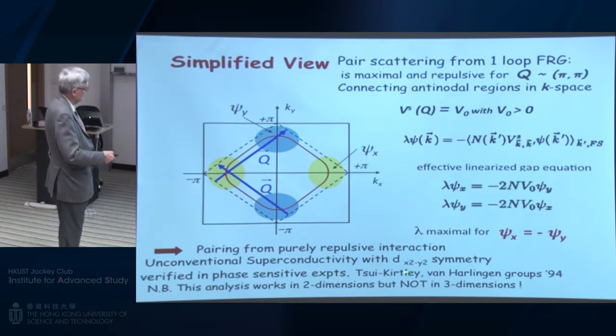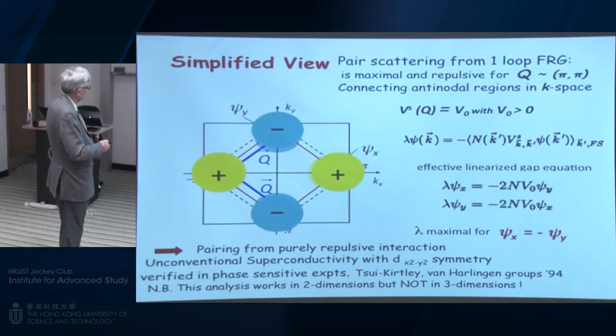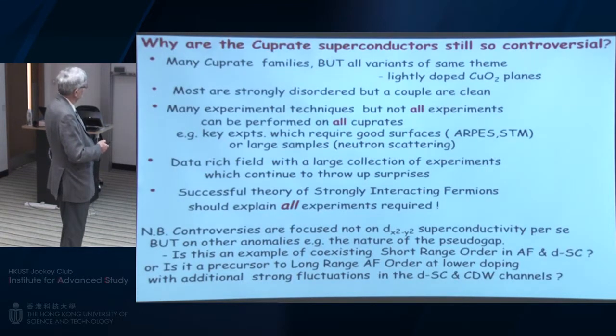It should have this extra phase, and this was then verified by beautiful phase-sensitive experiments in the mid-90s that I don't have time to go into. But one thing I would point out: this nice analysis only works in 2 dimensions. If we had a third dimension, like a 3-dimensional cubic with another saddle point up the z-axis, we can't have all of them exactly opposite signs, because this one cannot be opposite sign to both of these at the same time. So 2 dimensions helps.